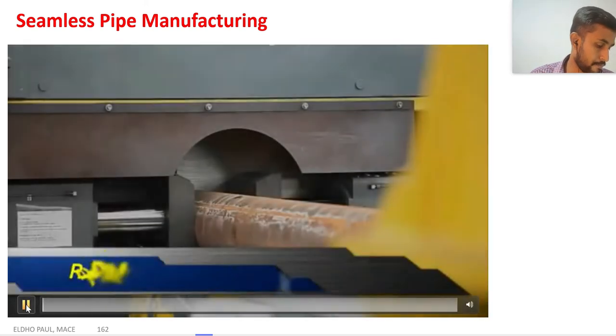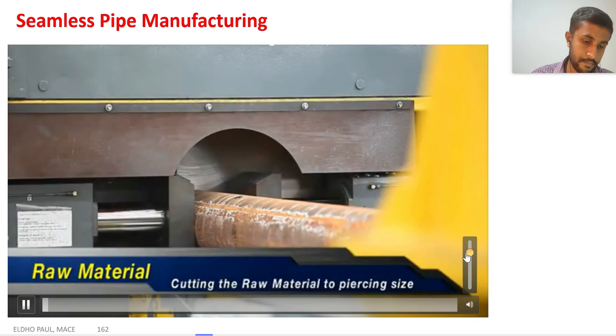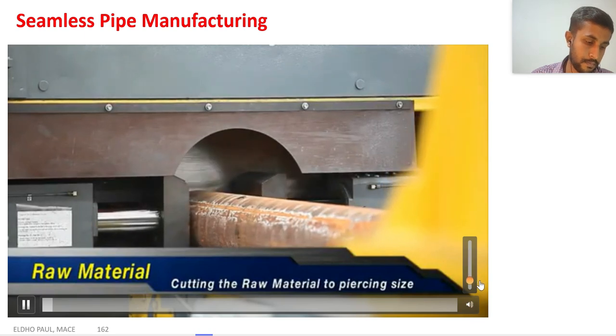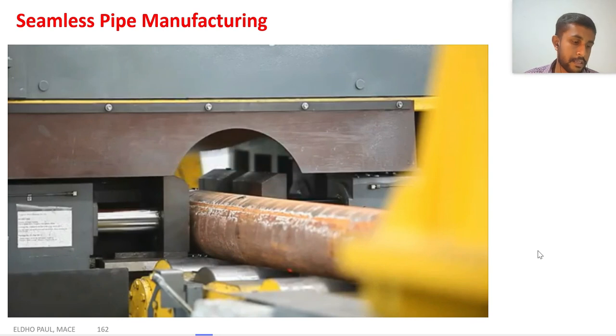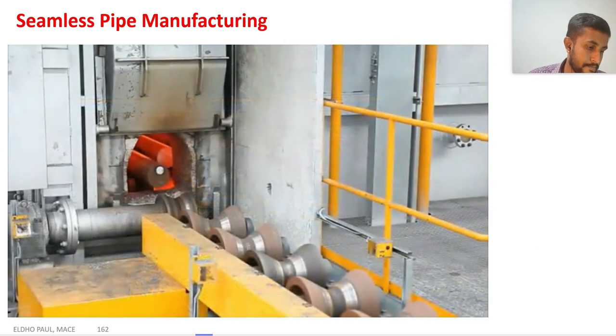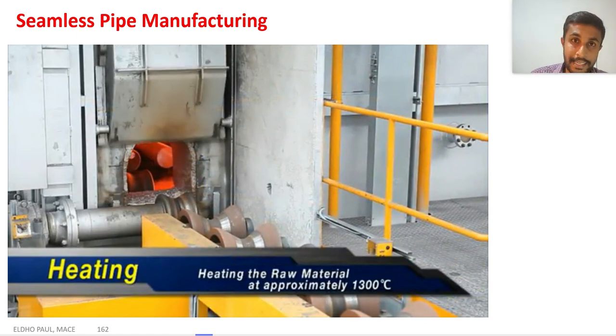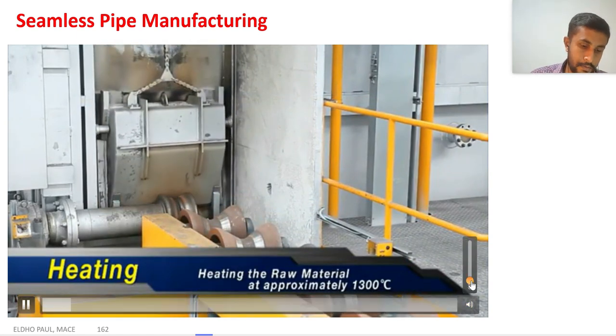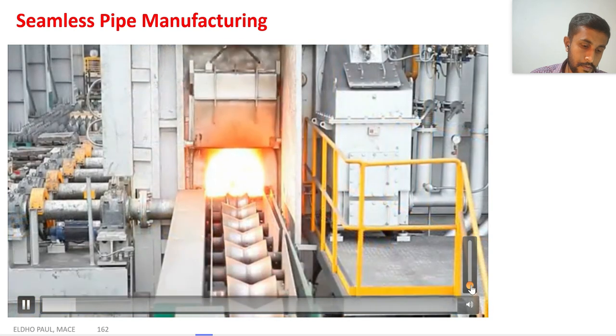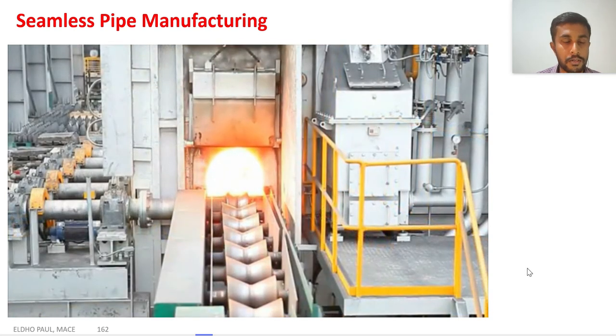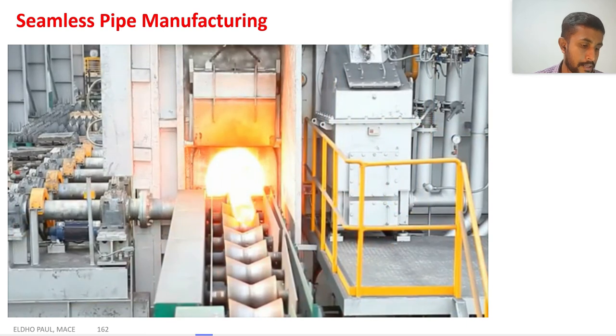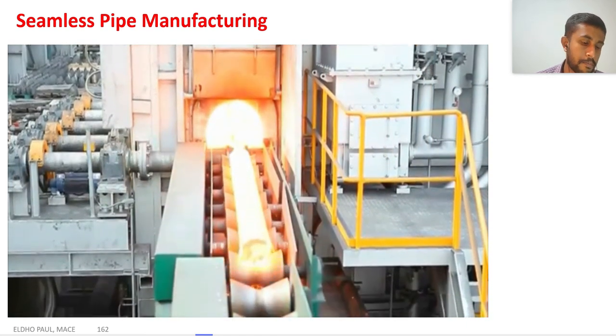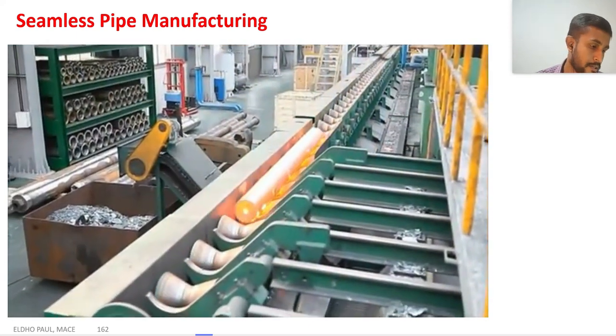Next, we will see how this final product is produced, how seamless pipe is manufactured in an industry. So this is the billet used for pipe manufacturing. The first step is heating. After we heat it to 1200 to 1300 degrees Celsius, the next process is Mannesmann or rotary tube piercing.